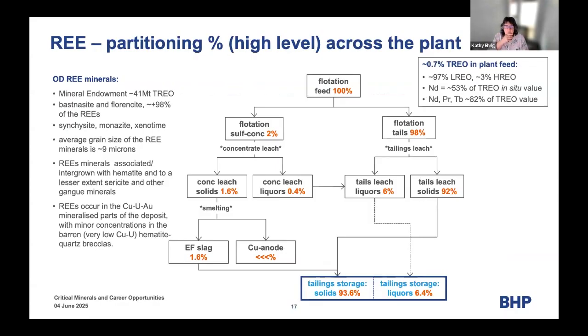So we're just going to use an example of rare earths, and we look in the upper right-hand corner. Typically, over the last 5 years, the total rare earth oxide feed into our plant is about 0.7%. 97% of that is light rare earth oxides. 3% is the heavy rare earth oxides. Neodymium makes up about 53% of the value of the total rare earth oxides. And neodymium, praseodymium, and terbium are 82% of the total rare earth oxide value. So it really is around a few rare earths.